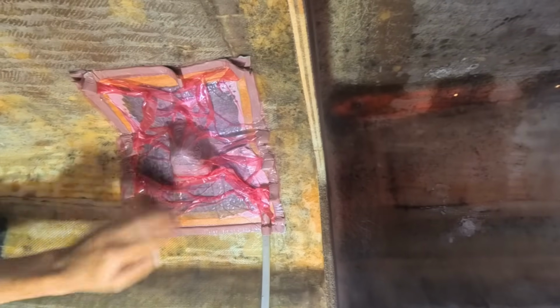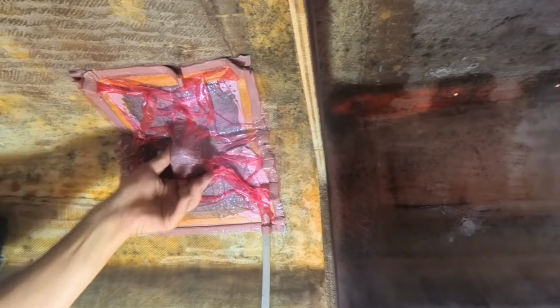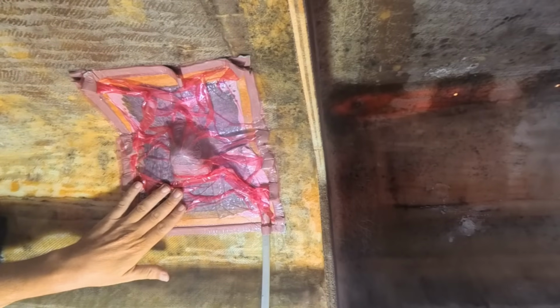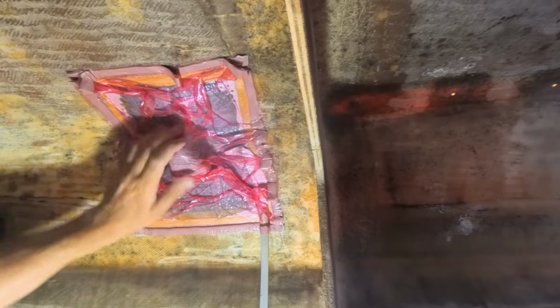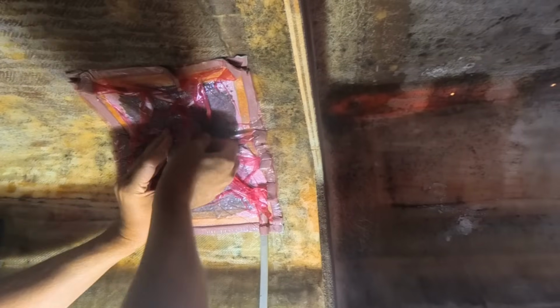But yeah, that's a very good bleed out. That bleed out is a bit too much, in that when I was laminating it was really wet, because it was a case of I have to laminate fast. Speed was the only way I could get this done while making sure that it didn't go off on me. So it is quite wet. So I just smashed all the resin on, knew that it was really wet, and I knew it was going to float a little bit on me, so whatever.